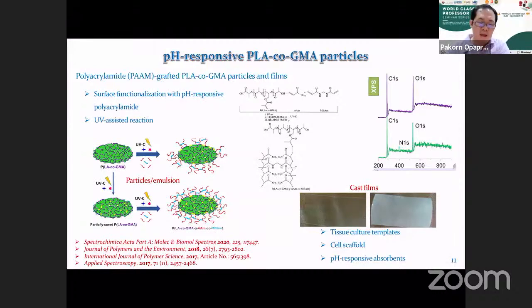However, we can also further modify the surface of particles that are made from this copolymer, because we know that this copolymer has a double bond. We can make them into particles first, and after that, we can further modify or graft some functional groups on the surface of the particles that are made from this copolymer.